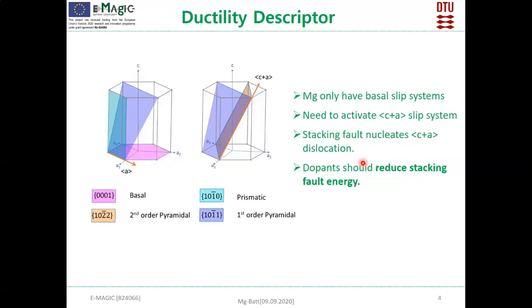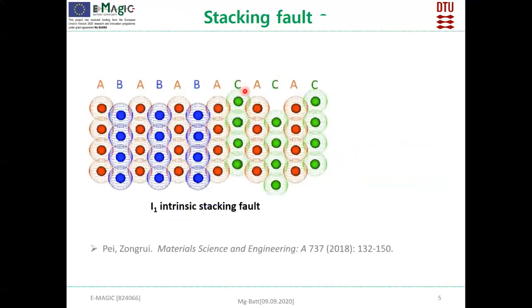So here we are looking for dopants which reduce the stacking fault energy on doping with magnesium. We compare the stacking fault energy of pure magnesium with that of magnesium with the dopant, and we check whether the dopant reduces the stacking fault energy. There are mainly three types of stacking fault in magnesium, but the I1 intrinsic stacking fault is related to the ductility. The I1 intrinsic stacking fault has a stacking sequence of AB, AB, AB, AB, then there is a missing B plane, and then comes an AC, AC, AC stacking sequence. The work of Pei et al. shows that this intrinsic stacking fault is correlated to the ductility of the magnesium material.